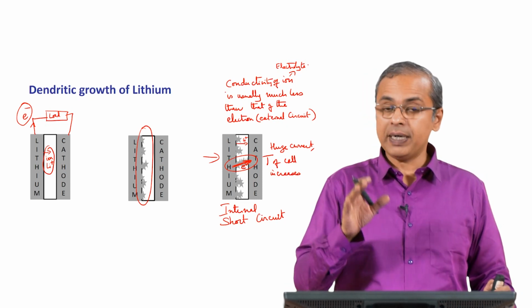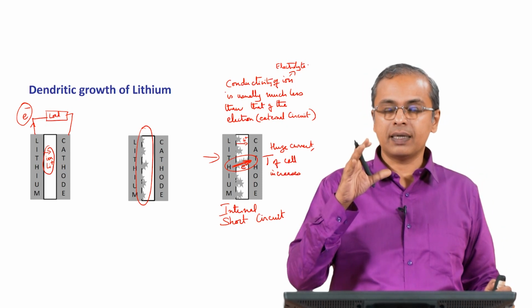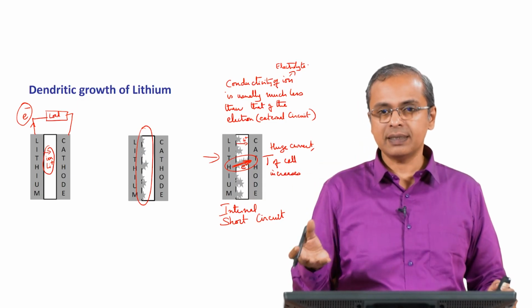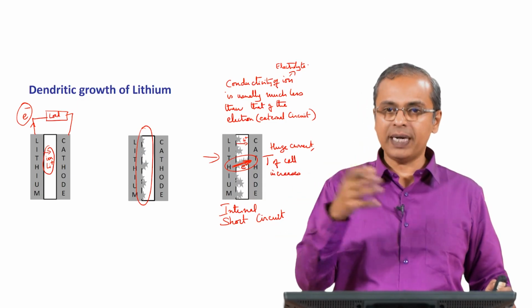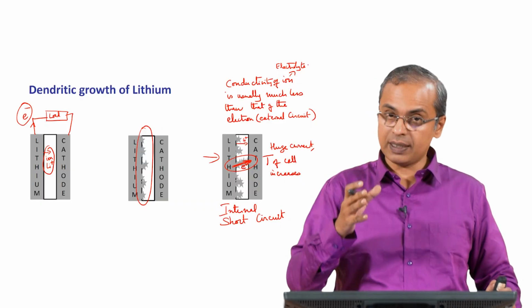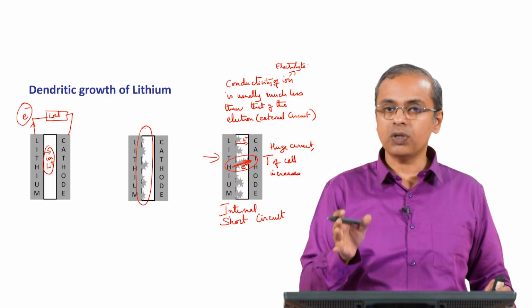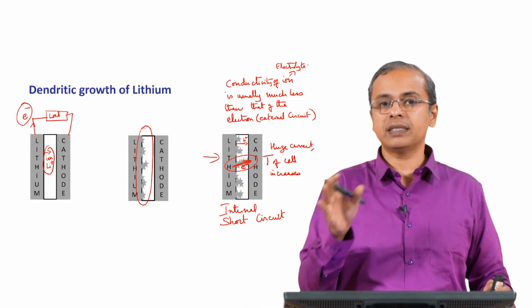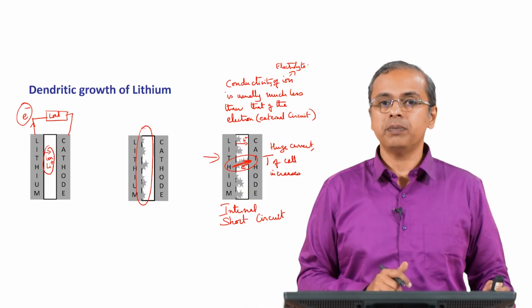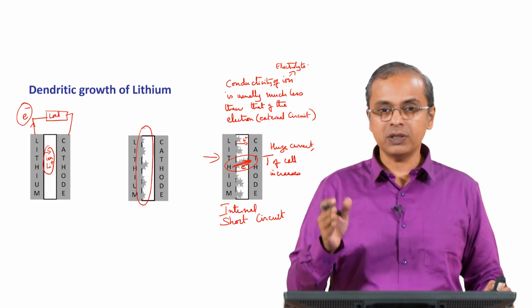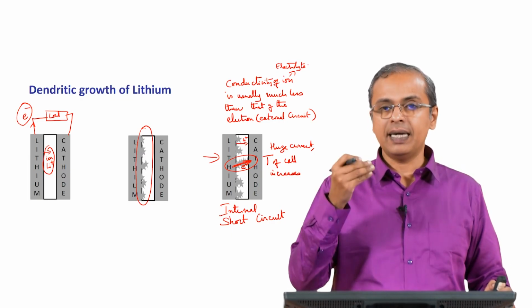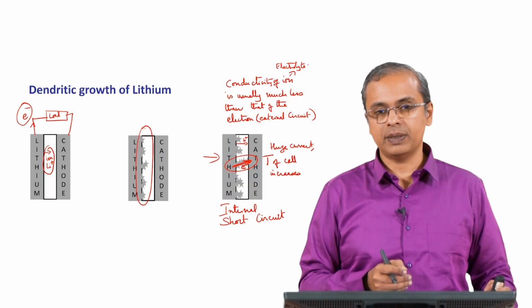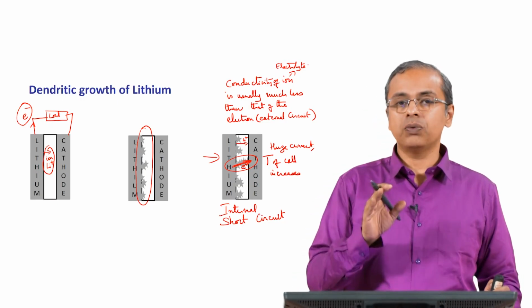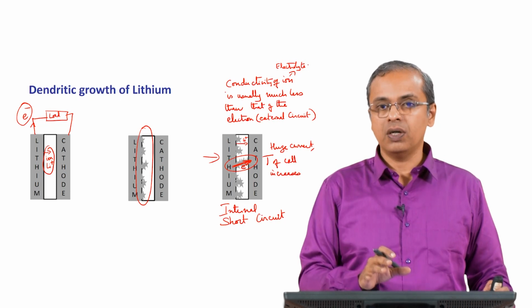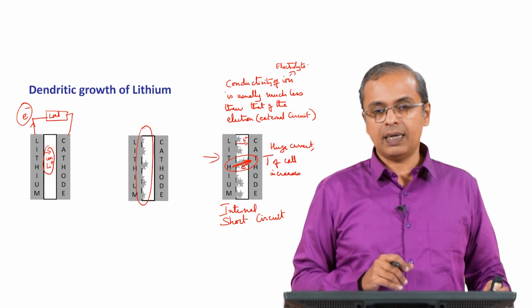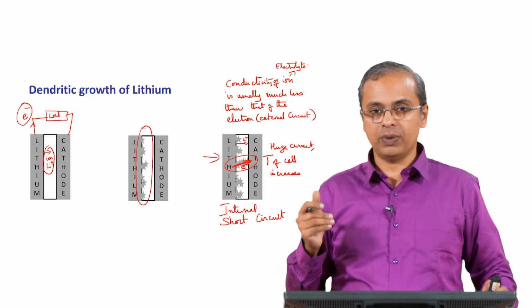So, this was a problem, but incidentally this is not a problem with single use batteries. Single use lithium batteries did not have this problem because you never plated it back, only when you plate this back you have this dendritic structure growing which can continue to grow and make this short circuit. So, it was not an issue with lithium single use, non rechargeable batteries, but it was a problem with lithium rechargeable batteries, and this was primarily because there was a plating stripping mechanism and this plating process was creating this situation. Therefore, they decided that using lithium metal as the anode was not a safe thing to do, because that required this plating and removal kind of thing.